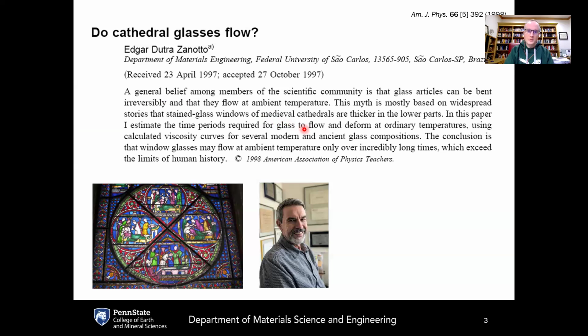And the main equation that was used at that time for measuring or for estimating the temperature dependence of viscosity was this Vogel-Fulcher-Tammann equation, or VFT equation. This was actually proposed empirically way back in the 1920s, and it relates the shear viscosity of a glass-forming liquid, and this viscosity is given by the parameter here, eta, to the temperature T, where there are three fitting parameters that are A, B, and T0.